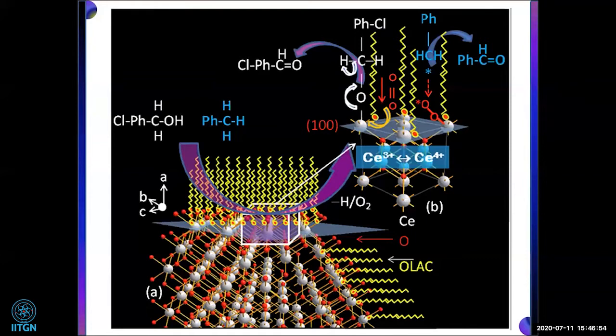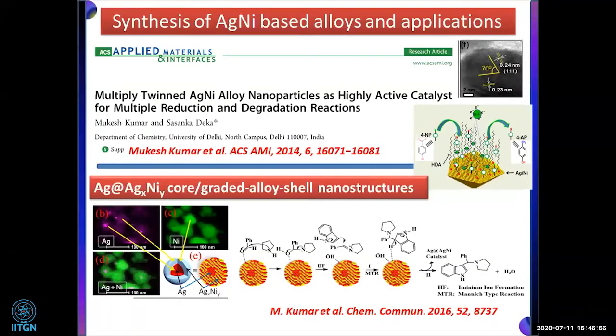the reactant molecule. Further, we have tried other nanomaterials, and we found that as compared to the bulk, say for example silver nickel alloy, because of the multiply twinned structure, it gives a lot of defects. And again, with the help of the surfactant, as I am saying, the importance of the surfactant is also there, because if we strip off the surfactant, if we heat the material and remove the surfactant, then we don't get any product. It means the catalysis reaction is zero.